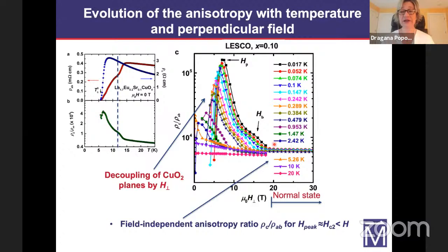So if you look at this curve and that curve, you can see that they're similar. What this is telling us is that the behavior is the same as we approach the superconducting transition, either by reducing the temperature in a zero magnetic field or by reducing the magnetic field at a fixed temperature. So in both cases, we see this enhancement of the anisotropy. So we again interpret this as the onset of superconducting correlations in the planes.